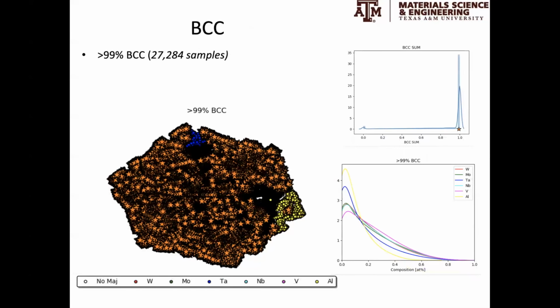If we look at the percentage of alloys that have more than 99% BCC, it turns out that again most alloys satisfy these constraints. So we're looking at alloys that tend to be mostly BCC throughout the composition range. Again, this tends to happen when we have alloys that do not have a lot of aluminum in them.